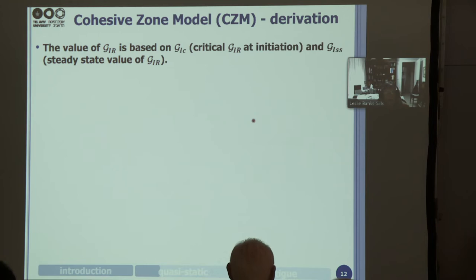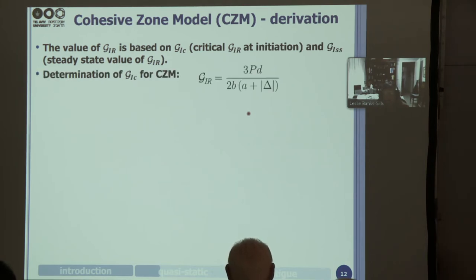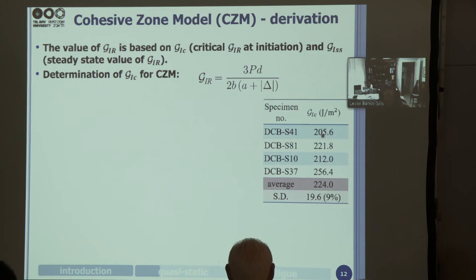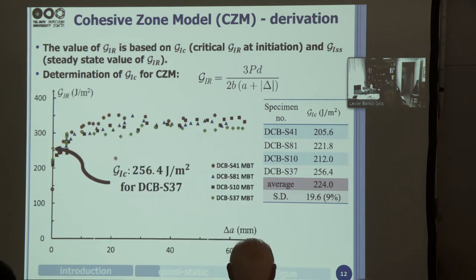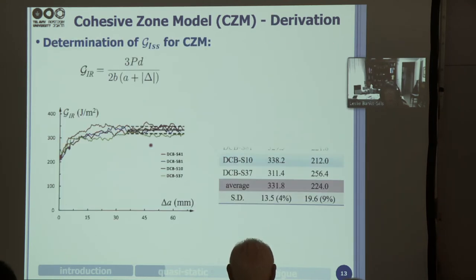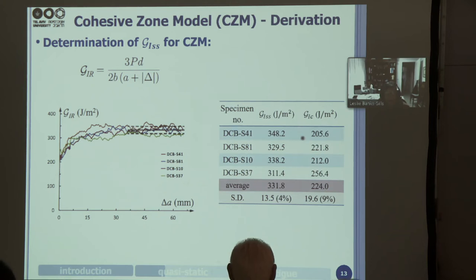So the value of G1R is based on G1C, which is the critical G1R at initiation, and G1SS is its steady state value. And we determine G1C from this equation, where R is replaced by C. And here are the values that we obtained, and the average value, and the standard deviation. And here you can see the G1R curve, and as an example for specimen 37, G1C, you can see the diamond-shaped point is 256.4 joules per meter squared. And then we do the same thing for G1SS when it reaches its asymptote. Here are the values for all of the specimens, and here is the average value.